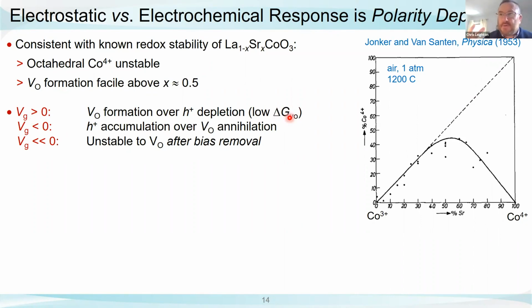But by the same token, when we reverse the electric field, it's unlikely that we can annihilate those very thermodynamically stable oxygen vacancies, but we have to balance charge. So the only option is to then accumulate holes on the cobalt. The cobalt valence goes up from 3.5 to 3.6 to 3.7, let's say. That's fine, but the minute we turn the bias off, then of course it becomes unstable again towards the formation of oxygen vacancies, which qualitatively explains the trends that we saw in those experiments.